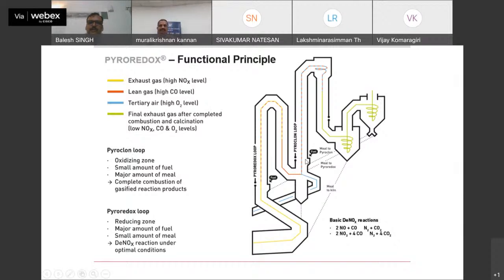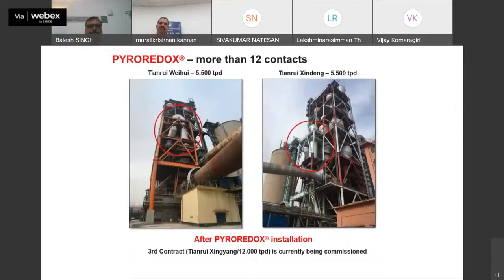which is being generated from the preheater, and then it enters the calciner where we inject the tertiary air, which was earlier in reduced condition. Now when it comes to the pyroclone, it becomes oxidized, and the calcination happens as per the normal calciner principle. So this way the NOx, which was produced inside the kiln, is being reduced by 30 to 40%, and the required norms can be fulfilled very easily.